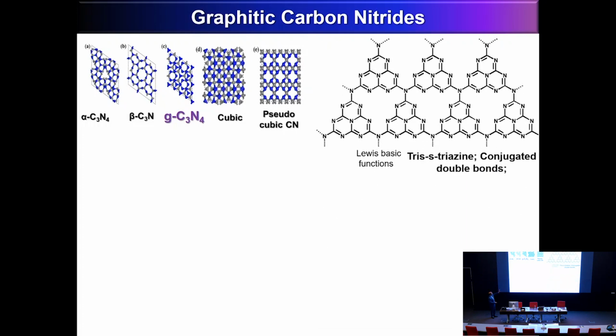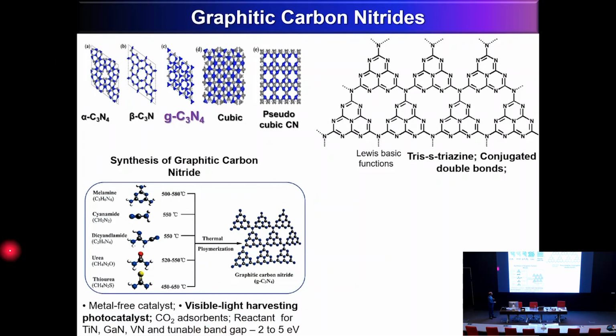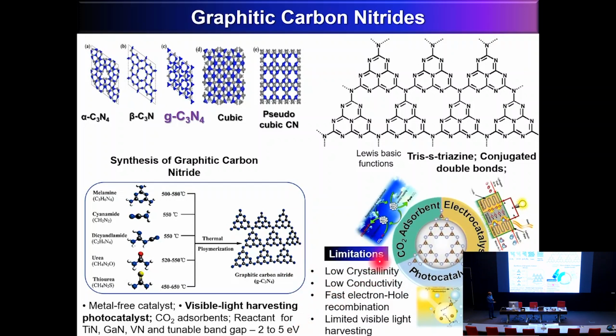Not only for its easy synthesis approach, but also it has a unique molecular structure with triazine and free NH2 groups on the surface, and it is a metal-free organic semiconductor with a band gap of 2.7 electron volts. And since it has a basic NH2 group, it can also be used as a basic adsorbent for capturing CO2. So how to make this material? This material can be fabricated by just burning out a high nitrogen containing organic molecule under an inert atmosphere, and you will get graphitic carbon nitride, but with a low surface area. Even with the low surface area, people have been using this as an adsorbent, electrocatalyst, or photocatalyst.